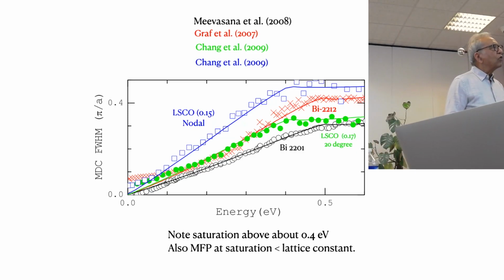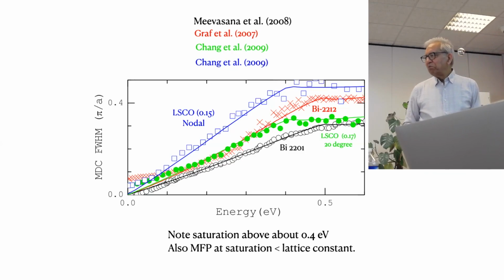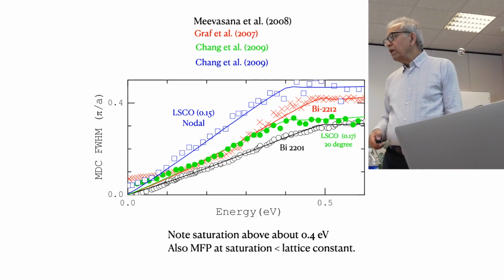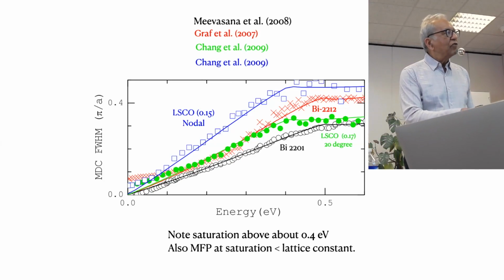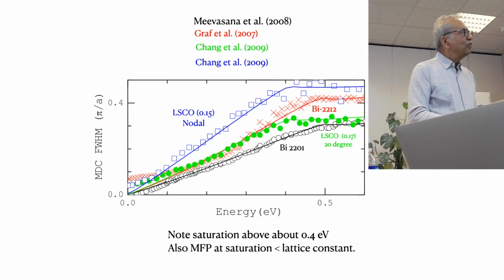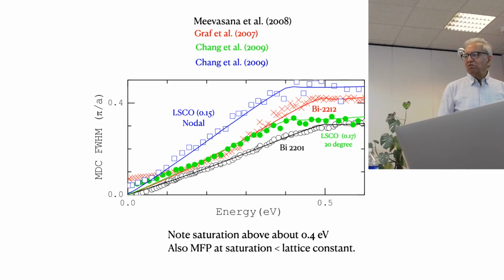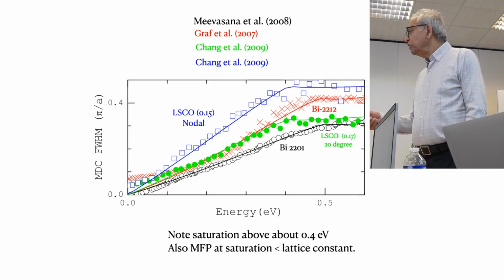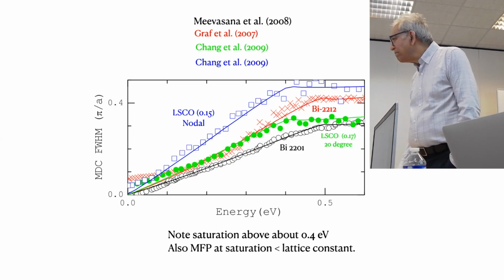And these are all the 4 compounds which have been measured by various people, and you find that the scattering rate within some error bars is linear, and then it saturates. And there is this slope, and there is this cutoff, okay? The cutoff is on the scale of 0.3 to 0.4 eV, and if I take the sensible Fermi velocity to convert that also into energy units and get the slope in dimensionless units, that slope is varying between 0.4 and 0.5. Okay? So again, for which doping, what is the regime?